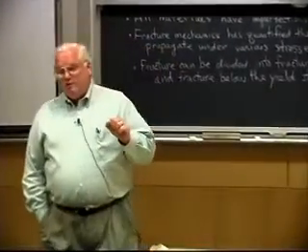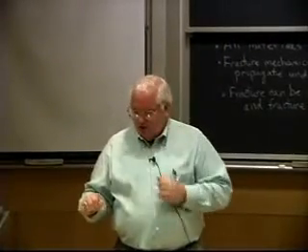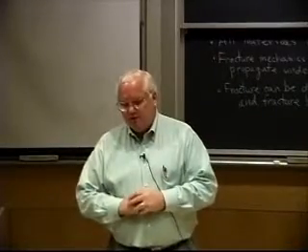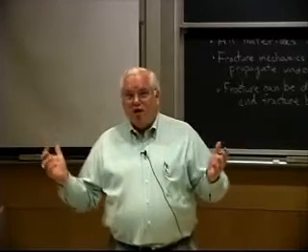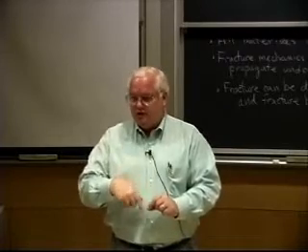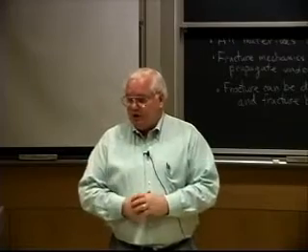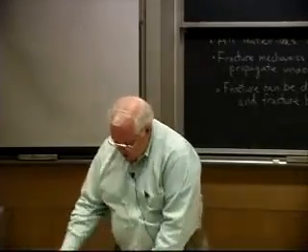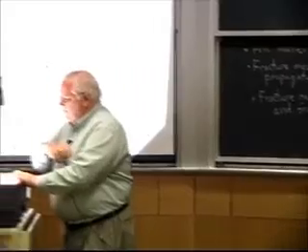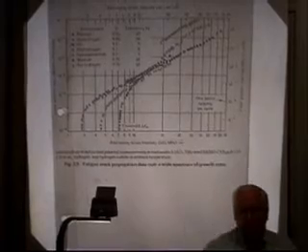When I was a graduate student, another graduate student came to me because he was shifting on his, I think he had a Ford, and he had a shift in the center console, a manual transmission, and the thing just broke off, okay? And I looked at it, and sure enough, it's a fatigue fracture, and it was because, in this case, they had just screwed the thing in, and it had failed at the stress concentration, but they had also plated it. And if you remember that plot I showed you, they electroplated it. They chromed it, right? In this case, by looking at the fracture, when you're just shifting, you shouldn't have any high stresses.